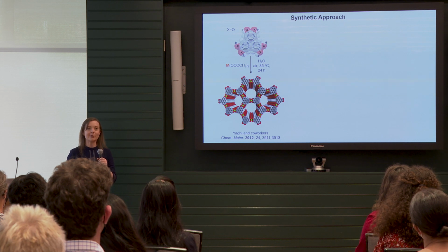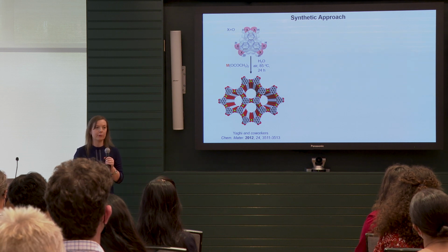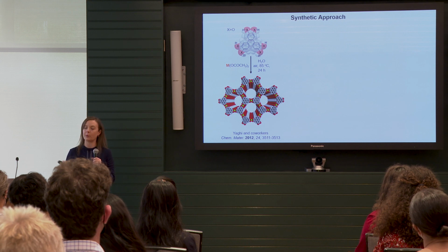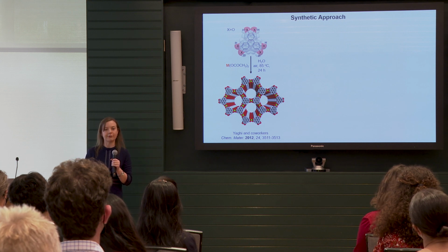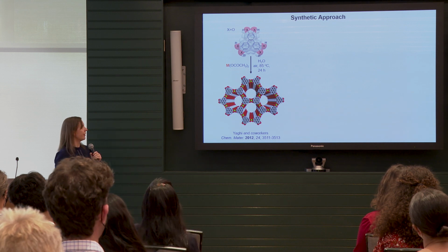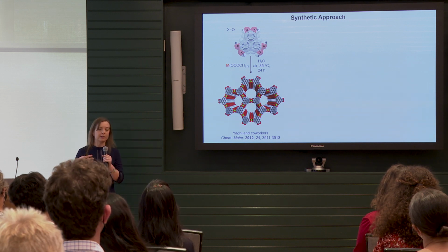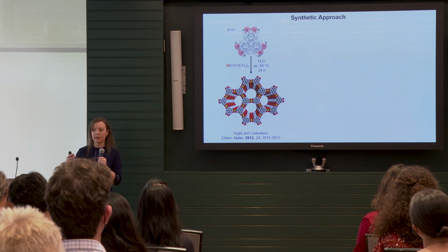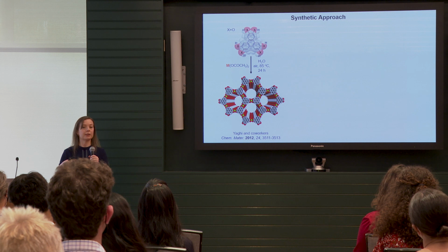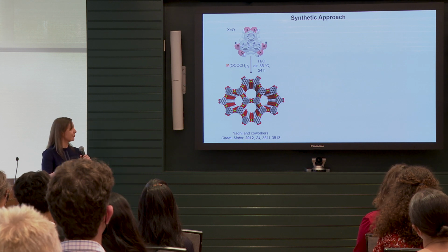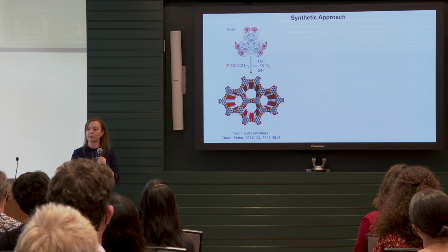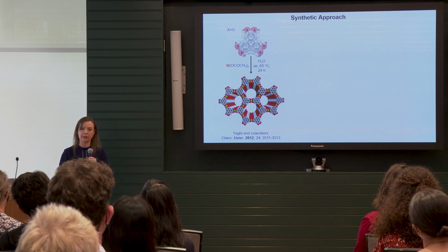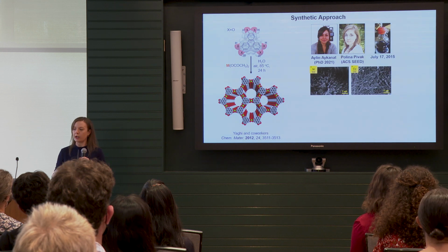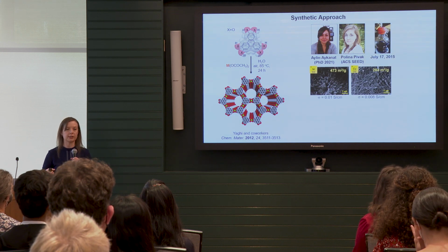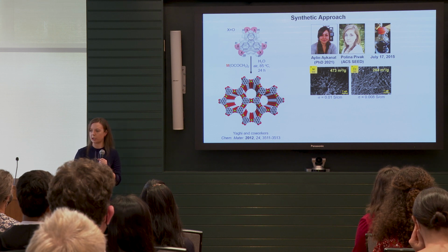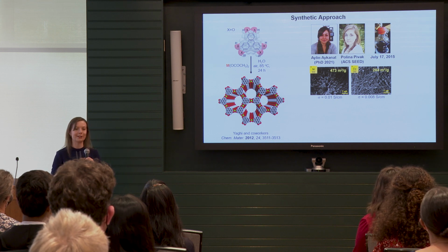The nice thing is that these materials are extremely straightforward to make. Pretty much every student in my group who's come through this group at one point or another has made these framework materials. We can start with a commercially available hexahydroxytriphenylene and run a reaction that proceeds in water, under air, with some heat, in the presence of oxygen. So it's just like cooking. It doesn't really get more complicated than that for this particular material. And from those synthetic conditions, through a self-assembly process, we're able to obtain conductive and porous nanowires of the self-assembled framework material.